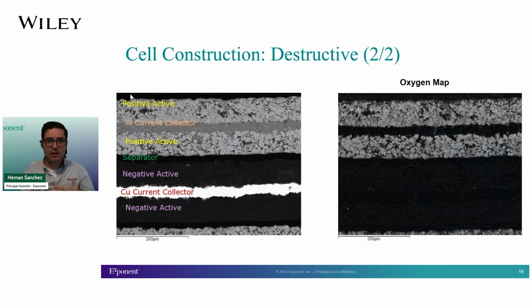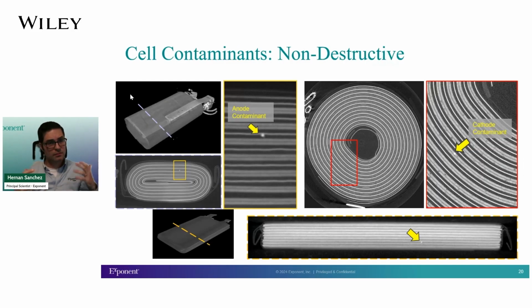On the destructive end, there is also a lot of value that you can get out of doing cross sections. In this case they are physical cross sections, but there were some great examples from the ion mills to do cross sections of cells, and you can get an idea of what your particles look like, of your current collectors, of your thicknesses. There's a lot of information to be acquired, and once again, this is just baseline understanding of what your cells look like. And this plays fantastically into a previous conversation about how there are systems that can allow you to both detect the contaminant and then track it down. So these are two examples of finding the contaminants both in the anode and the cathode via non-destructive techniques.